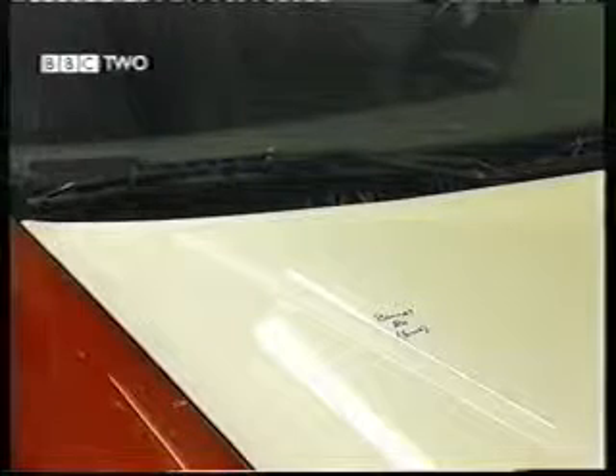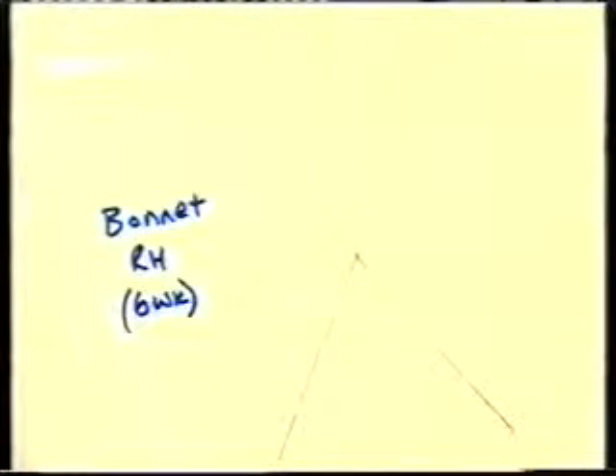Before the test, a panel was scratched like this. For vehicles with Rover's 3-year cosmetic warranty, after 6 weeks of testing, no more than a 2mm corrosion blister is allowed to have spread from the cross scribes. Well, that may satisfy the warranty requirement, but did the metal have to rust at all? Here's the prototype of a bonnet panel that has been protected with a zinc coating front and back. Not much of a corrosion blister here.